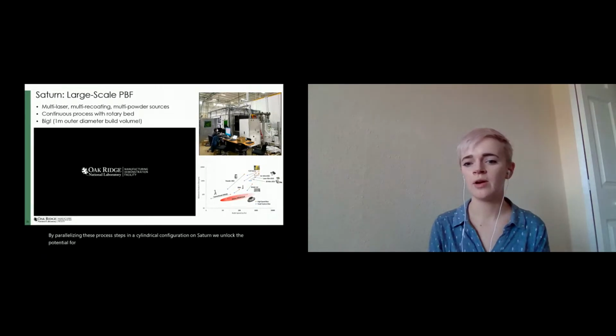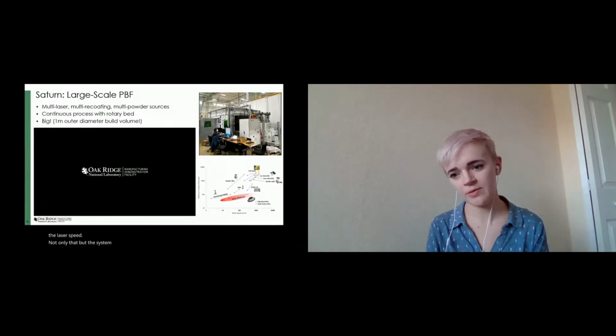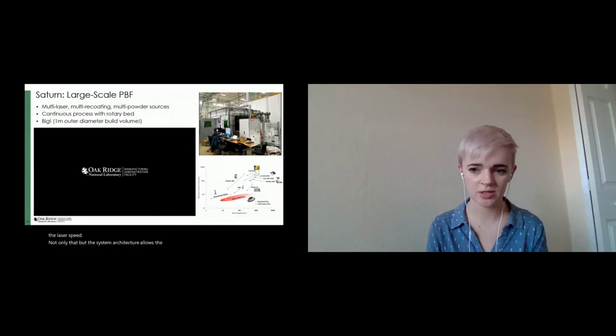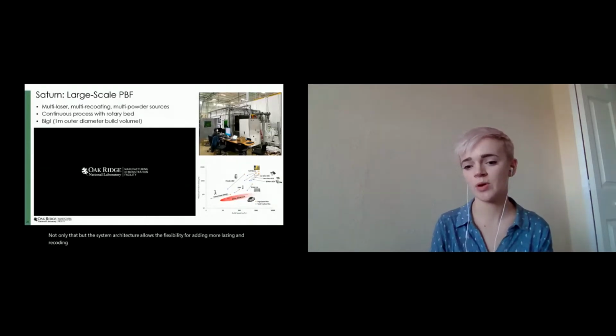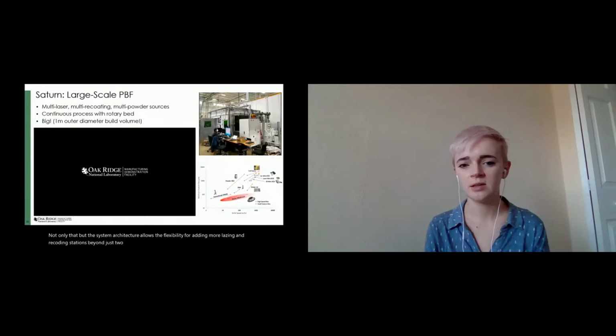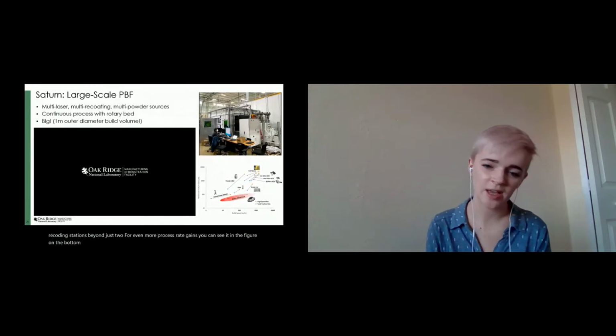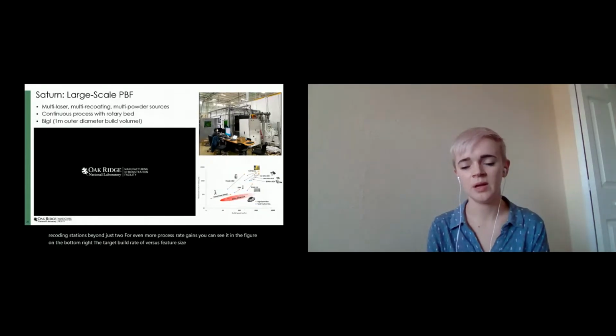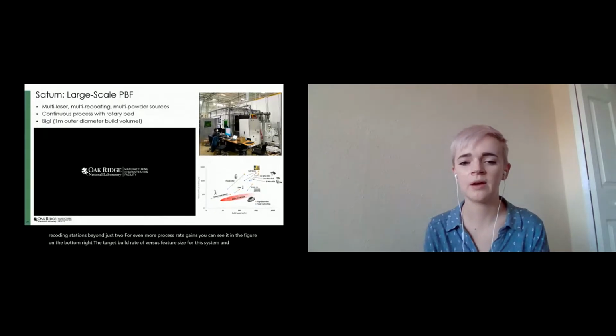By parallelizing these process steps in a cylindrical configuration on Saturn, we unlock the potential for much higher build rates that are not limited by the recoating time, but rather by the laser speed. Not only that, but this system architecture allows the flexibility for adding more lasing and recoating stations beyond just two for even more process rate gains. You can see in the figure on the bottom right, the target build rate versus feature size for this system and systems similar to this would be that red zone.